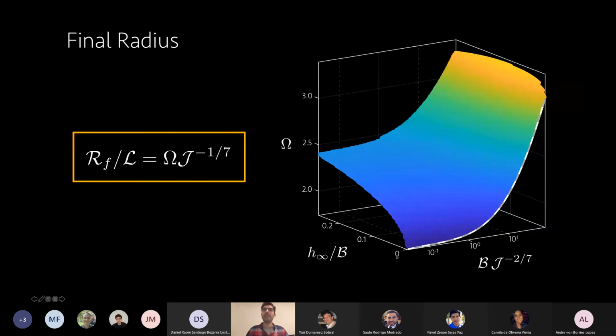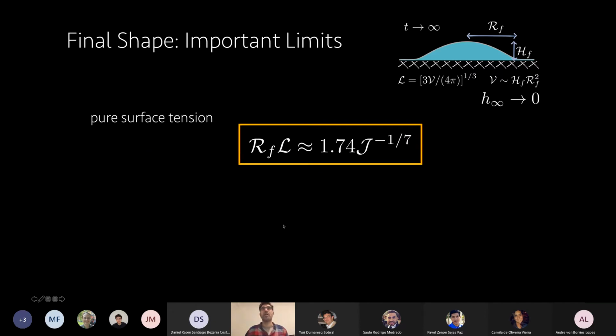Okay, and this line that I'm showing here is a very interesting limit where film thickness goes to 0, right? So if you have a fully wetting solid surface. Okay, so there are two interesting limits. If you have only surface tension, if your droplet is very small, here is your magic number, 1.74. You can get your final radius.